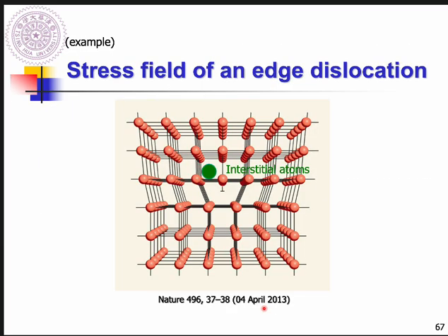But if we give you the other example, what we have here is an edge dislocation inside these materials. And we also have dopants, interstitial dopants. Because you have an edge dislocation, this region is a compressive region, compared to this one, the bottom, which will be a tensile region. So this stress gradient will induce the migration of these interstitials.